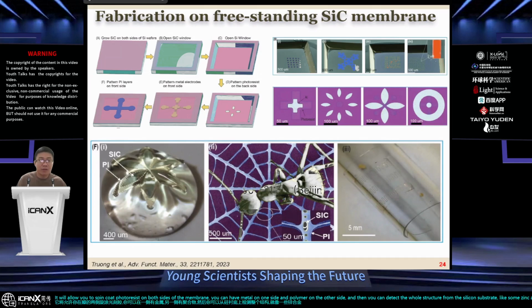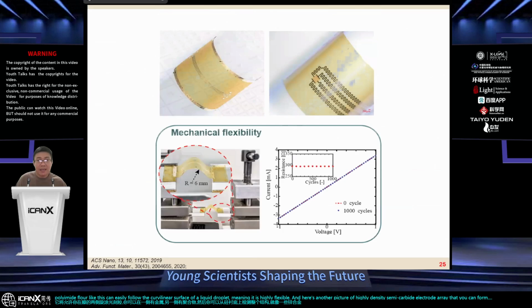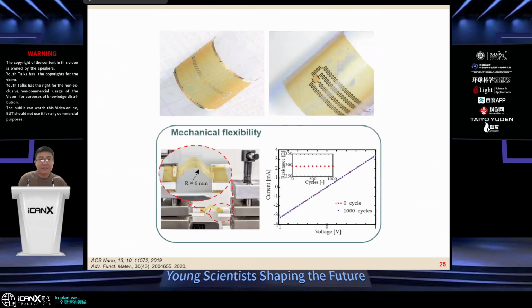It can easily follow the curvilinear surface of a liquid droplet, meaning it is highly flexible. And here's another picture of a high-density silicon carbide electrode array that you can form on a polymer substrate. And then for flexible implants, we also investigated mechanical properties. So we used the bending test to confirm that the electrical property of the material is very stable after several stretching and bending cycles.